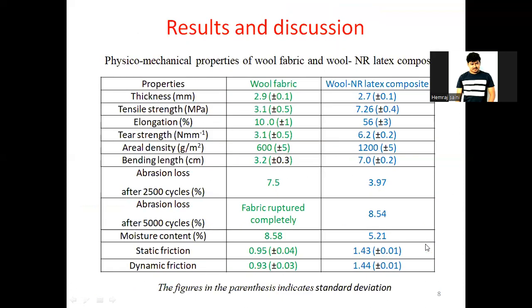Now coming to the results and discussion, these are the physical and mechanical properties of wool fabric in comparison with the wool natural rubber latex composite. What we observed is that tensile strength for bare wool fabric is 3.1, and it increased to 7.26. Elongation increased from 10% to 56%, because as we know rubber is highly elastic in nature.